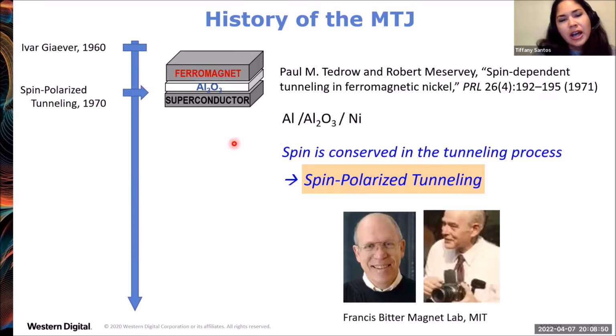A little while after Ivar Giaever's work, in the Francis Bitter Magnet Laboratory at MIT, there were Paul Tedrow and Bob Meservey. They were also using aluminum electrodes and aluminum oxide tunnel barriers, but this time the aluminum was the superconductor. And they had the idea of using a ferromagnetic nickel counter electrode. And with this tunnel junction, they showed the asymmetry of the spin density of states from the ferromagnet tunneling into the superconductor. This was the first experiment showing that spin is conserved in the tunneling process. And that's something that we take for granted now, as tunnel junctions are so prevalent in applications. But really, this was the first experiment to demonstrate that, and it broke open the field of spin polarized tunneling.